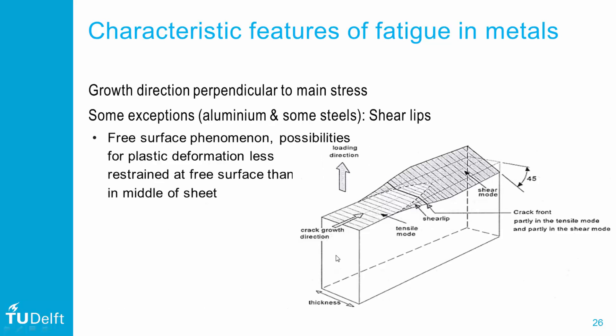Although crack growth occurs mainly perpendicular to the principal stresses, in thin sheets and plates one may observe shear lips at the surface. At the surface, plastic deformation is less restrained, which allows the fracture surface to tilt to 45 degrees towards the surface. This forms shear lips at the surface, which in thin sheets may result in complete tilting of the fracture plane.